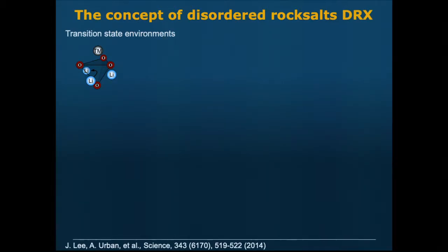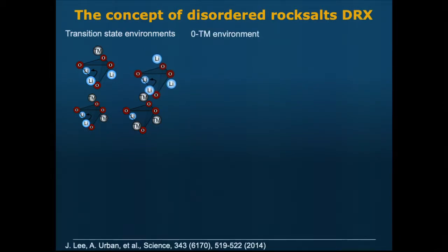What if you could change the transition state, right? If you just look at the different possible populations around the transition state, you could have more transition metal, but you could also have less. If you have enough lithium around, in principle, maybe you could make transition states with only lithium around them. And now you're in a better situation, right? Because when lithium diffuses in here, remember this one and this one would be vacant, it now only sees another 1+ ion. So now you have a 1+ ion seeing another 1+ ion, so your electrostatics is going to be much less. So hopefully you will be much more tolerant to contraction of this tetrahedron, right?